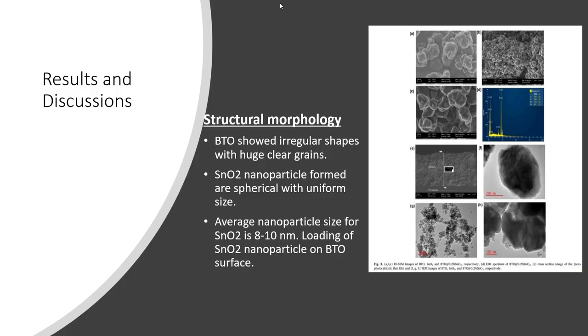Next up, we're going to discuss the structural morphology and elemental composition determination. FESEM was used to capture micrographs of BTO, SnO2, and the BTO at 0.2% SnO2 composite to get their morphological structure. And the TEM images of BTO, SnO2, and BTO-SnO2 composites. The tiny particles observed on the surface of BTO-SnO2 composites are SnO2, confirming the loading of SnO2 nanoparticles on the BTO surface.